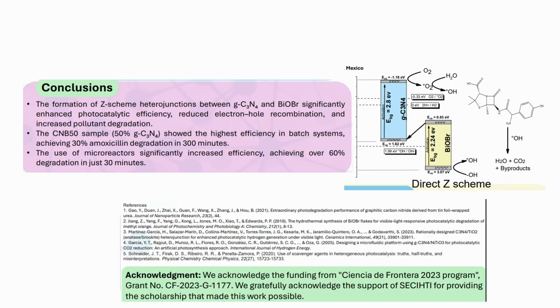As conclusion, we can say that the formation of Z-scheme heterojunctions between carbon nitride and oxybromide significantly enhanced photocatalytic efficiency, reducing electron-hole recombination and increasing pollutant degradation. The CNB50 sample, 50% weight of carbon nitride, showed the highest efficiency in the batch system, achieving 30% of amoxicillin degradation in 300 minutes. The use of microreactors significantly increased efficiency, achieving over 60% degradation in just 30 minutes.